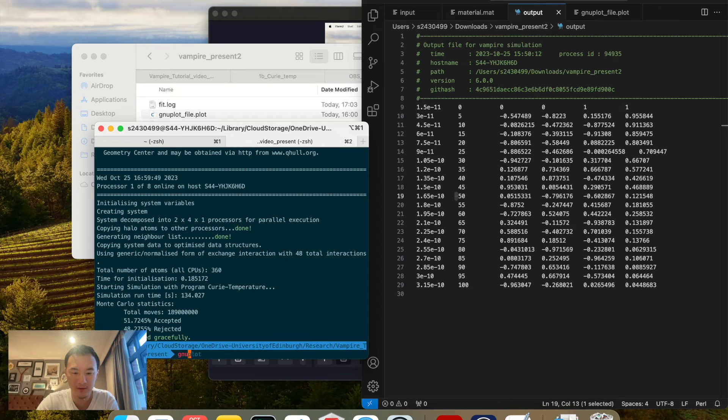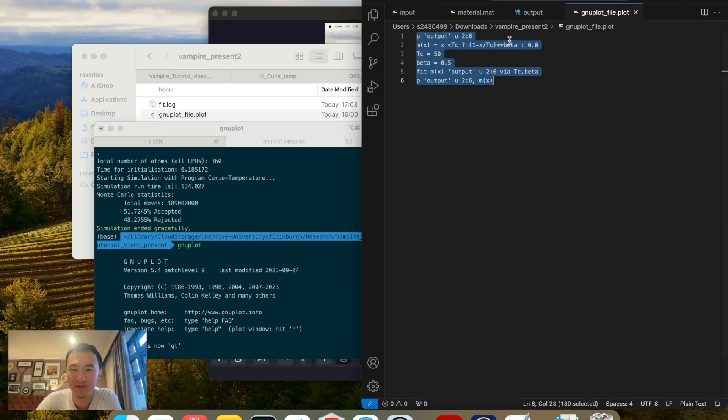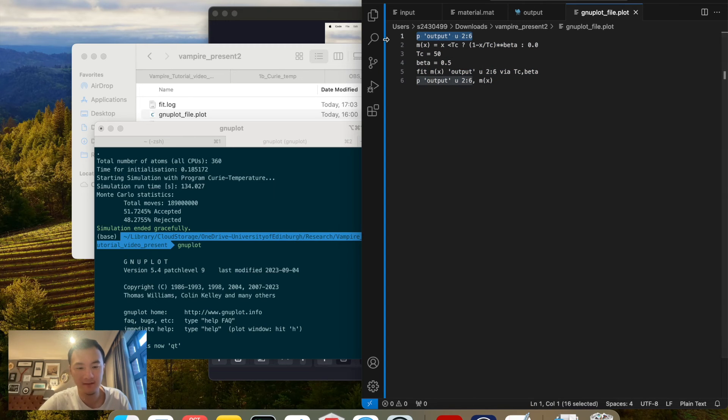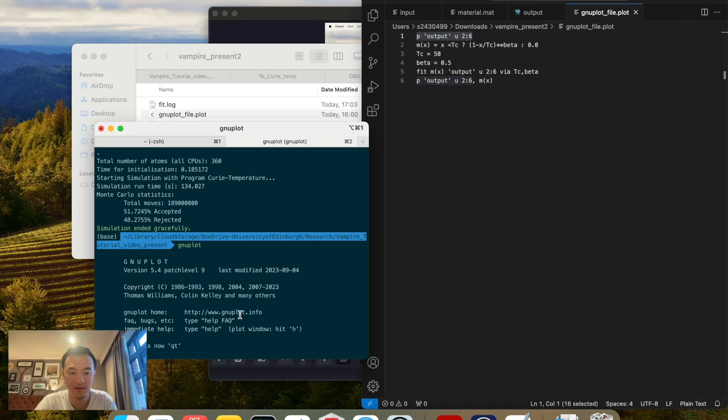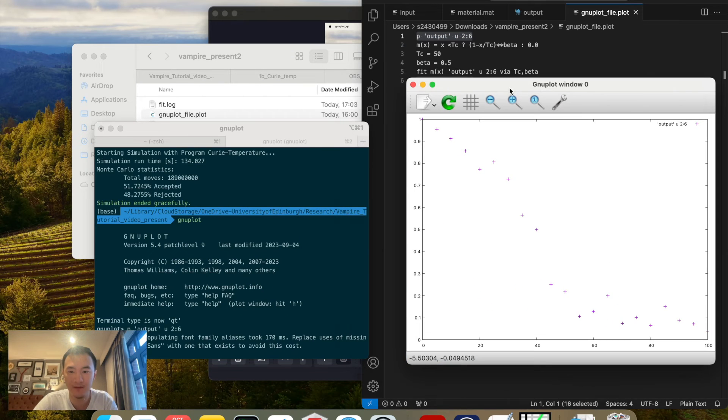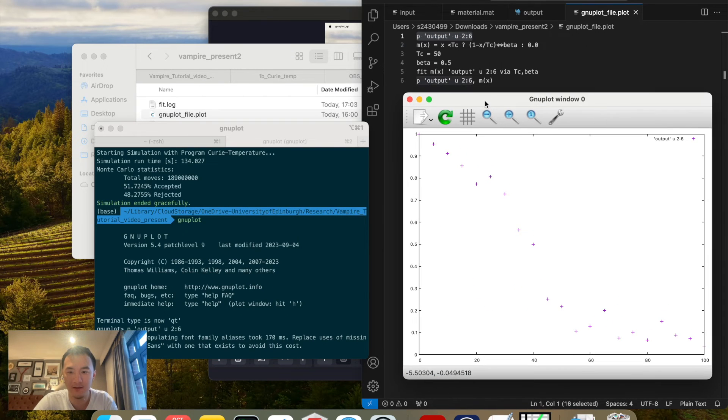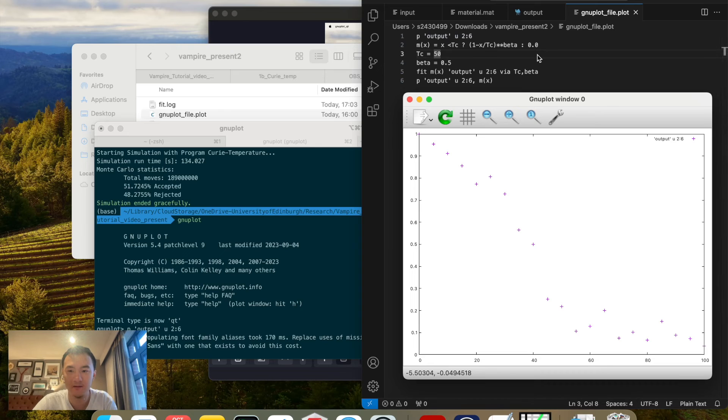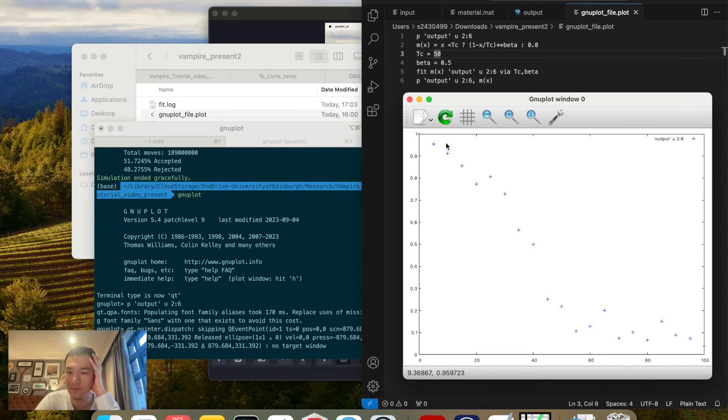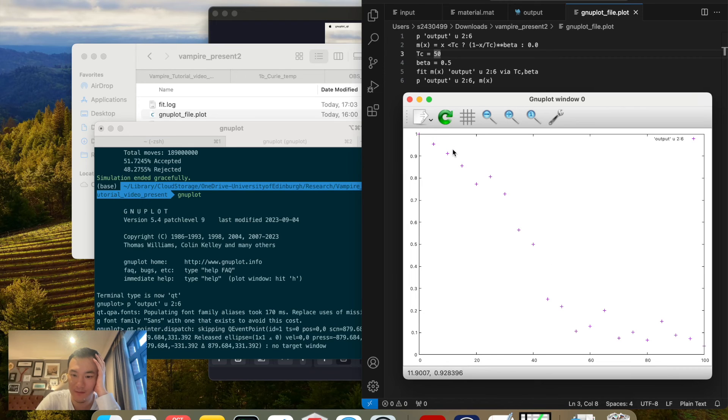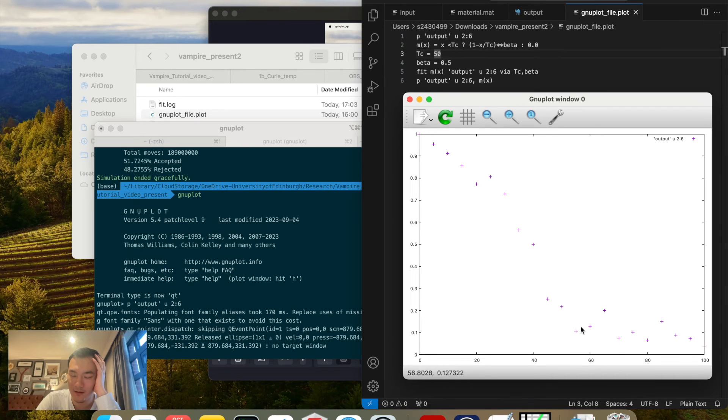Let us plot that data and see how it looks. We use gnuplot, and I'm going to use the same plotting commands that Richard Evans was using to make sure you don't get anything unknown. We can see that magnetization versus temperature graph decreases. I would say Curie temperature around 55 or so, and then it bounces back up a little bit. It is a common thing that for this type of two-dimensional materials that are close to the Curie temperature, you would need actually a lot more time, more computation to get an accurate answer.